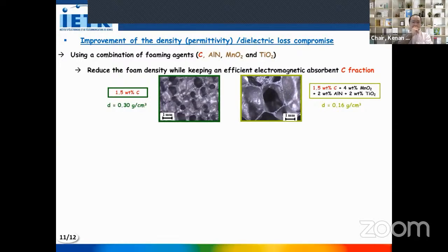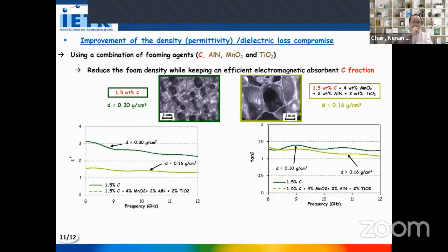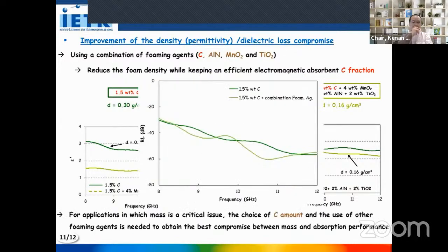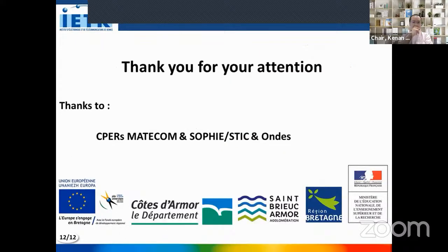Here are presented photos of samples made, the first with only carbon and the second with a mixture of foaming agents. This last sample presents a very low permittivity while maintaining a high level of losses, which induces high absorption performance. This allows obtaining the best compromise between mass and shielding efficiency.